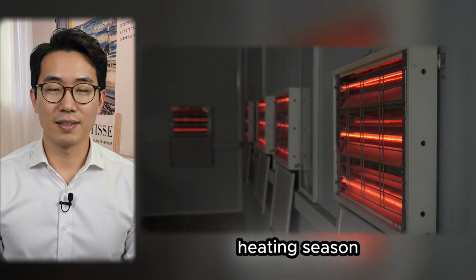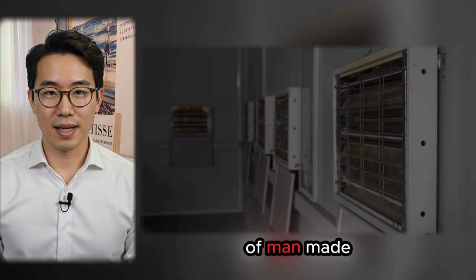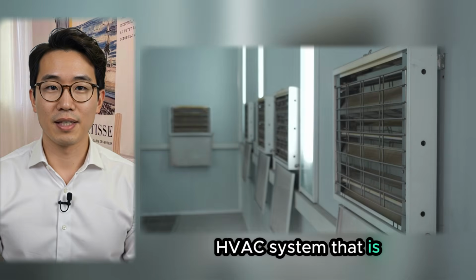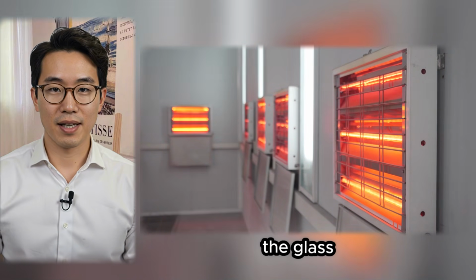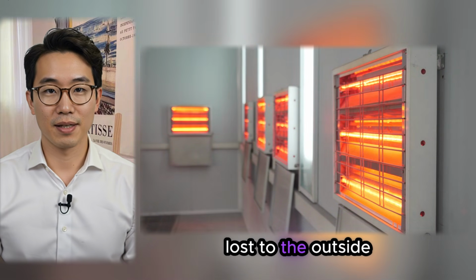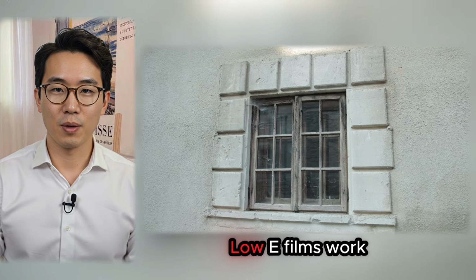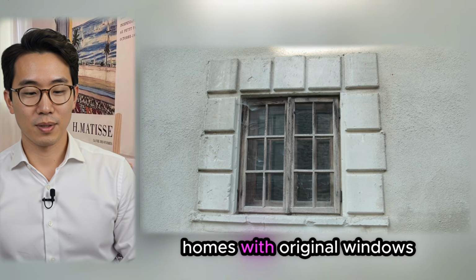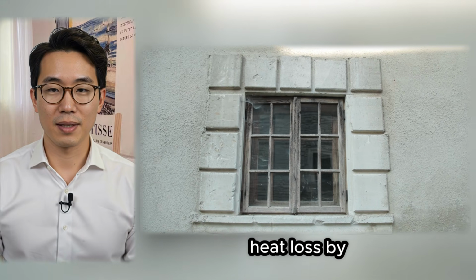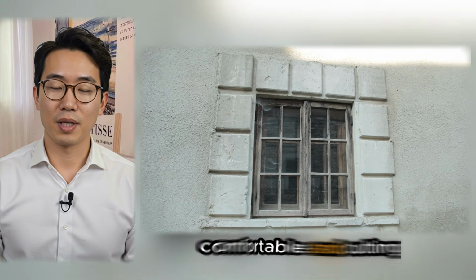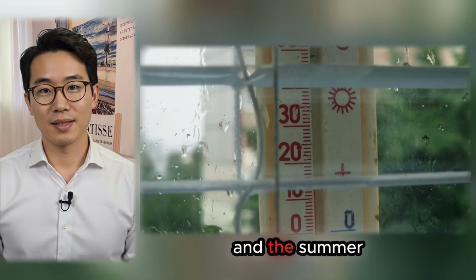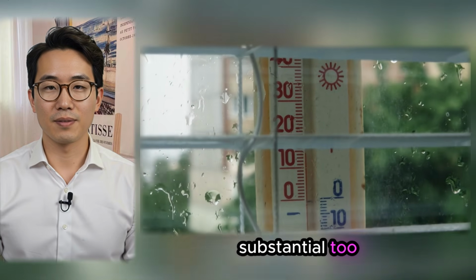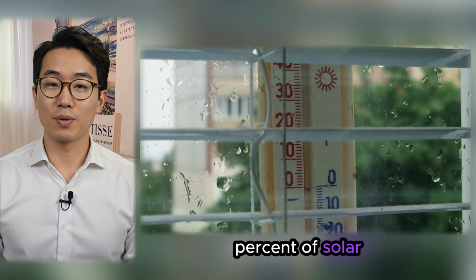And during the heating season, window film increases the amount of man-made heat from the HVAC system that is reflected back inside the glass, thereby reducing what is lost to the outside. Low E films work particularly well in older homes with original windows. They can reduce heat loss by 30 to 50%, making rooms more comfortable and cutting heating costs. And the summer cooling benefits are substantial too, typically blocking 40 to 60% of solar heat gain.